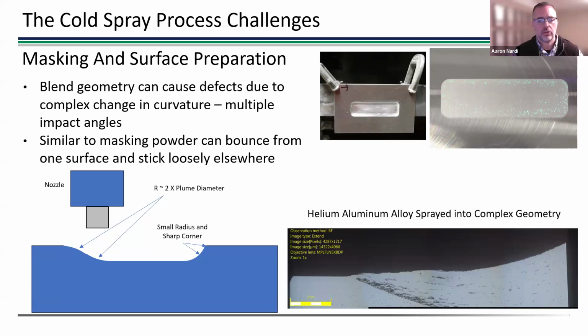And that's because you have a fairly small radius, and you're using kind of a flat raster pattern to spray there. So those secondary particle impacts, and especially when you're dealing with aluminum and spraying it with helium, there's a lot of energy in those particles. And if they do bounce off of a shallow angle impact, they still have enough energy to stick somewhere else. They just don't have enough energy to deform and bond well. So now you've got these defect sites.